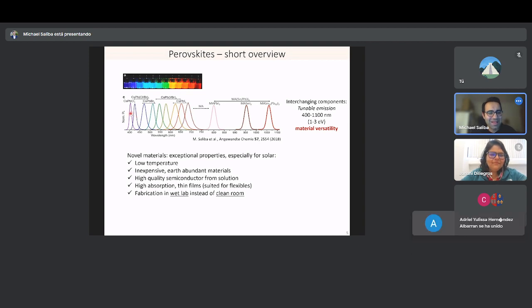And by interchanging one, or all three, of the components, going from cesium lead trichloride all the way to cesium lead iodide, the entire visible range can be covered, from 400 nanometers in the ultraviolet to about 700 nanometers in the red. And even by mixing parts of tin into the lattice as well, it's possible to go to the near infrared towards 1.1 electron volts, similar, maybe a little higher than silicon-based photovoltaics.